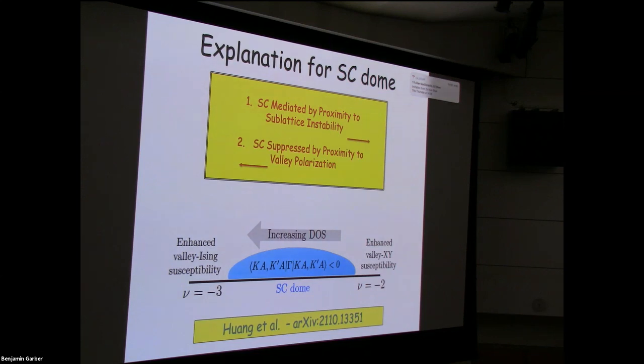this combined with the fact that the density of states goes to zero at filling factor minus two is at least a way of interpreting the superconducting domes that appear in these systems, and fits with quite a number of experimental trends. But we'll see, and Chun-Li will agree with me here. We'll wait and see whether this turns out to be the true story or not.